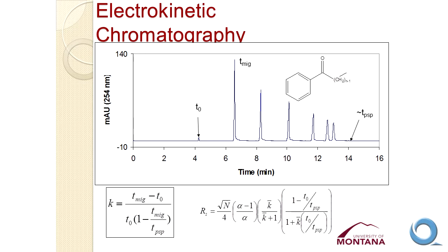It's a homologous series of alkyl phenyl ketones. And so each of these compounds is one more methylene group, and so a little bit more hydrophobic than the last. And so they are separated based on their affinity for the SDS micelles. And then out here, around 14 minutes, is where we would expect to see a compound that is fully associated with the micelles and does not come out of the micelles at all. All of our separations need to be done within this window.